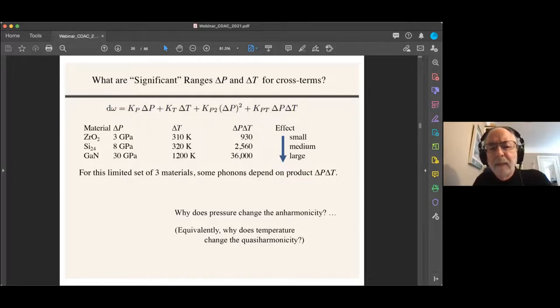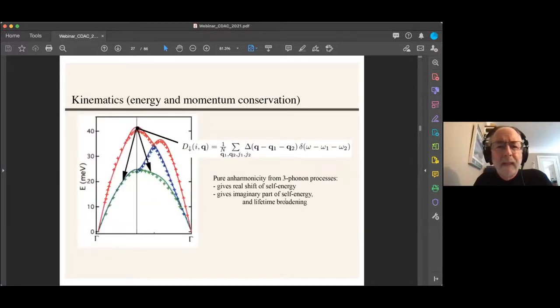But you may ask, why would you expect something interesting here? How does the pressure change the anharmonicity? Or likewise, how does temperature change the Grüneisen parameter or the quasi-harmonicity? Well, here's one explanation. Let's consider a three phonon process where we downconvert this optical mode into two transverse acoustic modes. And I've set it up so that the energies of these two ought to add up to this and the momenta ought to add up. So this is a typical cubic anharmonicity.